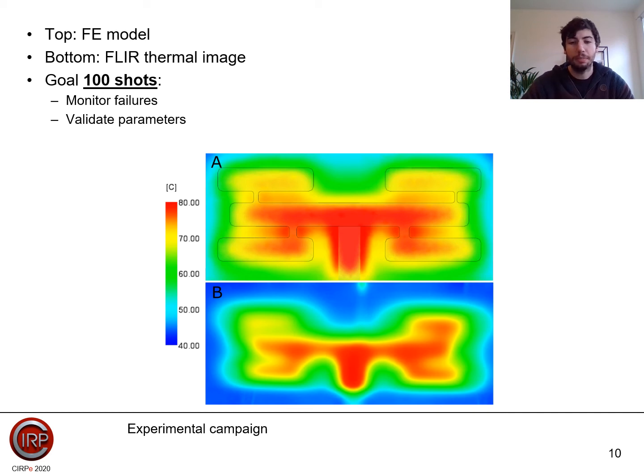The experimental campaign is both aimed at validating the proposed parameters as well as assessing the functional lifetime of the mold. The state of the mold and the temperatures are closely monitored between the consecutive shots. Due to the previously elaborated material tests, we were able to construct a model that is able to predict the temperatures quite well, which can be seen by the comparison of the thermal distribution in both the experiment and the finite element model.